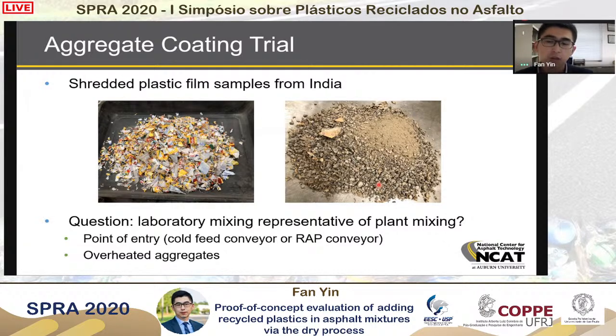the aggregate. So depending on where, once again, where in the drum inside the asphalt plant, the temperature of the aggregate can vary significantly, especially if we are producing mixes with RAP. Because of moisture content in the RAP, that can cause a significant reduction in the temperature of the aggregate. And that will affect the way the plastic interacts with the aggregate and eventually affects the property of the mix.